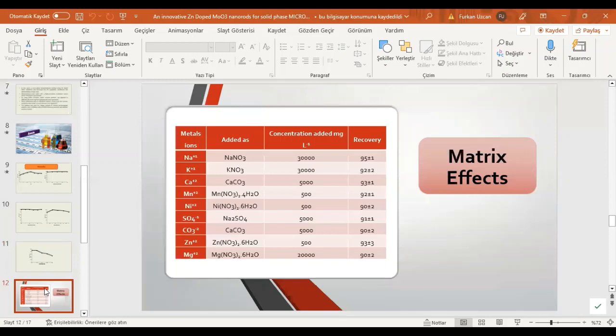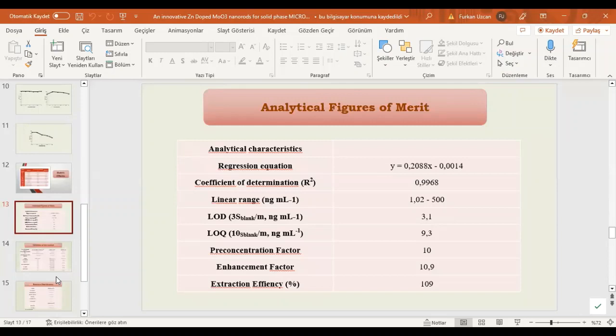Matrix effects we also studied. We added different cations and some anions at different concentrations separately. After that, we applied our method. As you can see on the table, the recoveries we got were above 90%. So we can say that our method is selective. As for analytical characteristics, as you see on the table, we got low limit of detection and limit of quantification.